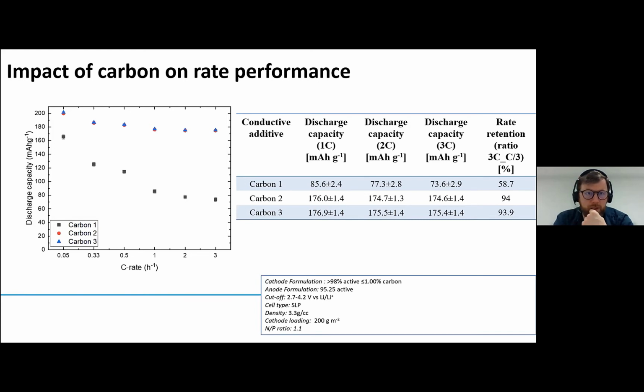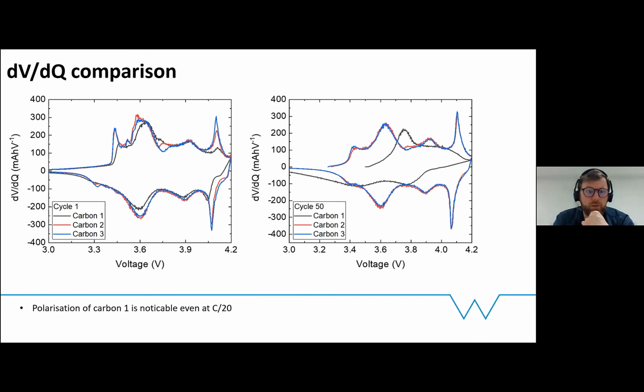It really is impressive. And you can see, as well as this, you get the structural stability of the coating as well. This is just showing the first cycle versus 50th cycle dV/dQ comparison. And this is looking at the polarization, and basically you can see that with just a normal carbon pushing at this type of formulation, the whole system is falling apart between cycle 1 and cycle 50, and even at the beginning it is still more polarized than that with the more advanced carbon additives in there.